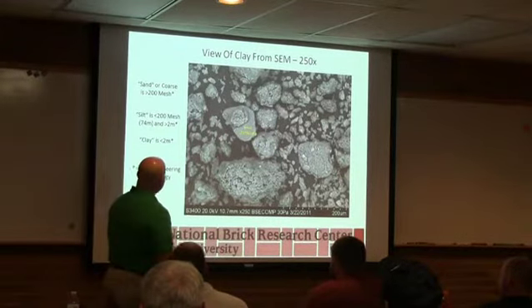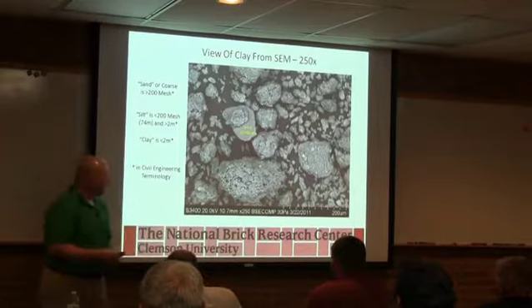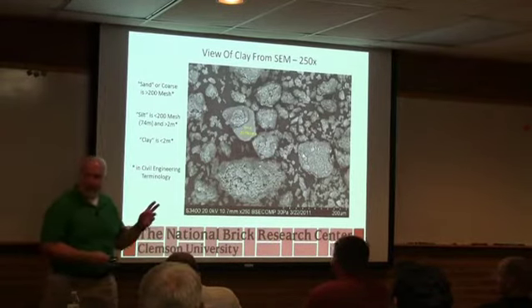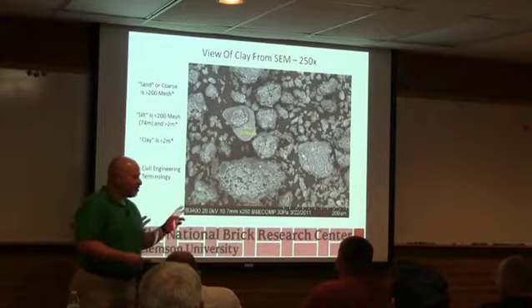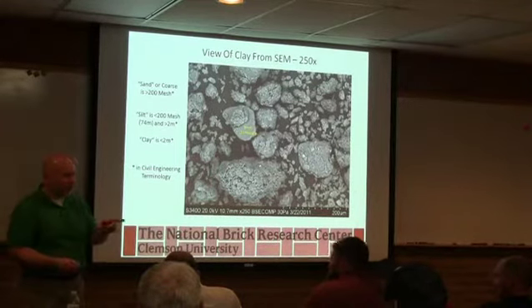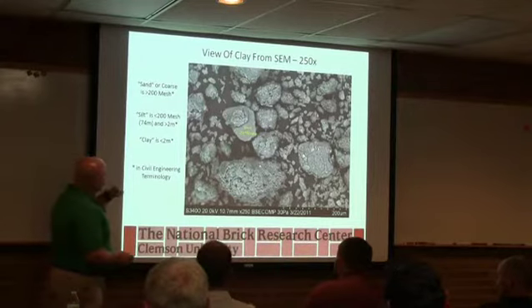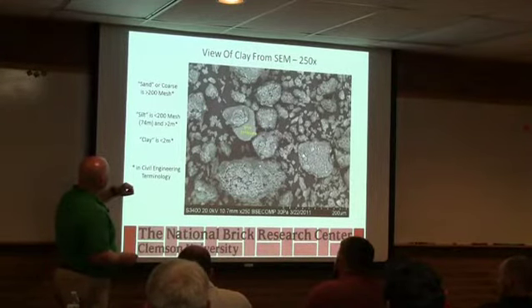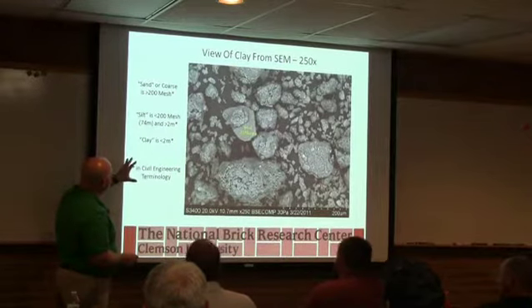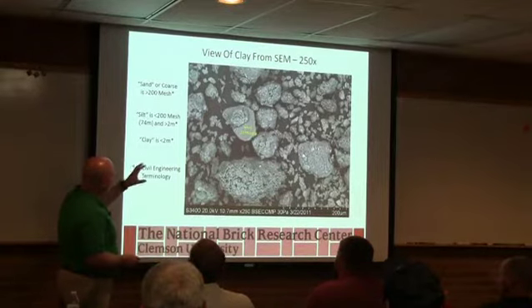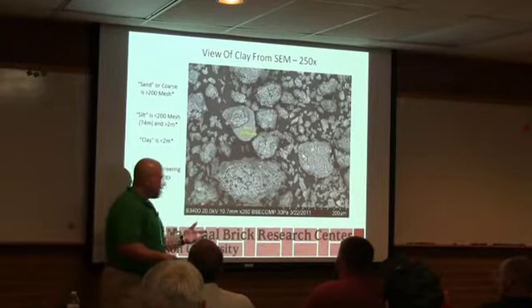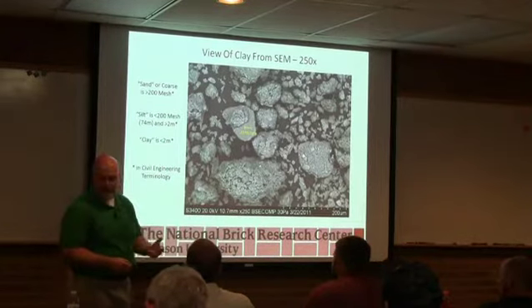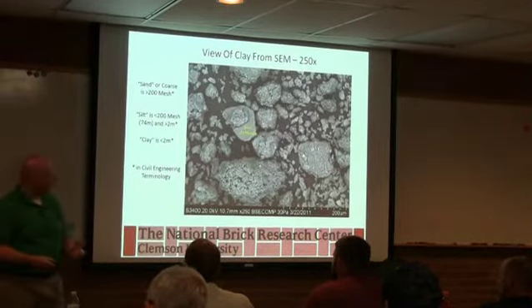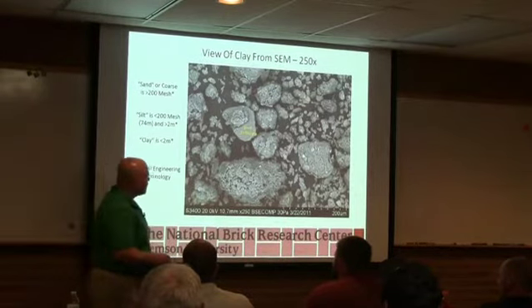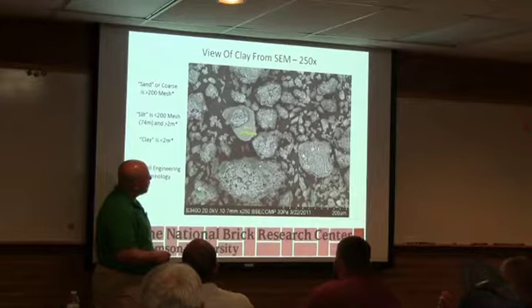So when we look at raw material, we typically break it down into 3 sizes. Anybody ever done a particle size analysis? Yeah. Where you break down the raw material? If you've been to the short course, we do that there. And we break it down into 3 sizes, and we'll talk about this as we go through. Each of these sizes is important. The first one's a little unfortunate because we call all of the coarse particles sand. And sand, you think of it's all silica, but it's not necessarily silica. It's the coarse particles. And typically they're going to help us control shrinkage and control size.